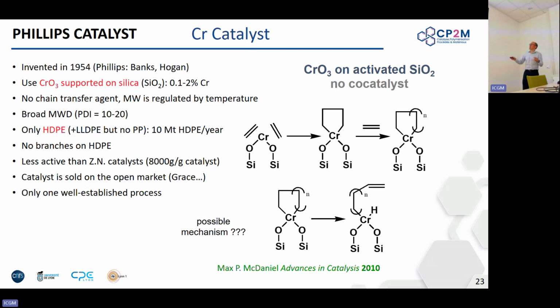In that case, the molecular weight, the molar masses are regulated by temperature. You have like a broad dispersity. You cannot really make things that are not ethylene based. Okay, so it's going to be mainly HDPE and a little bit of LLDPE, but no PP can be done. That's why it didn't grow as much as Ziegler Natta, and most people now use Ziegler Natta rather than Phillips, except for like some very specific products of polyethylene. Okay, it's slightly less active than Ziegler Natta catalyst, and the activation process is less understood.